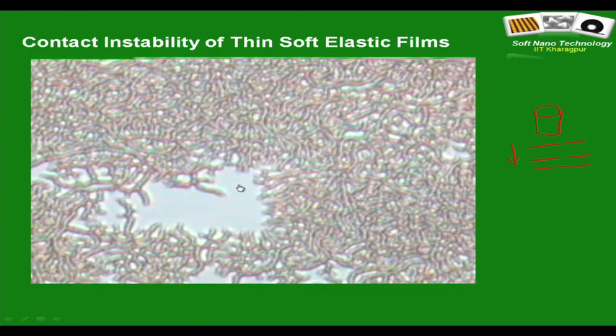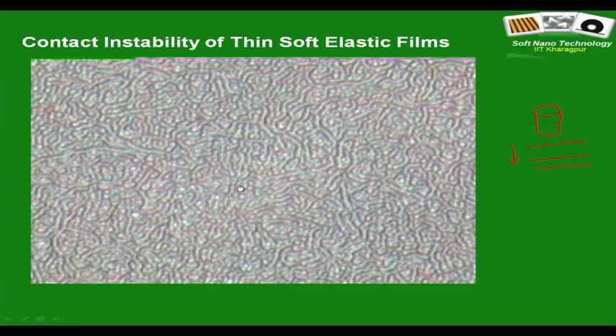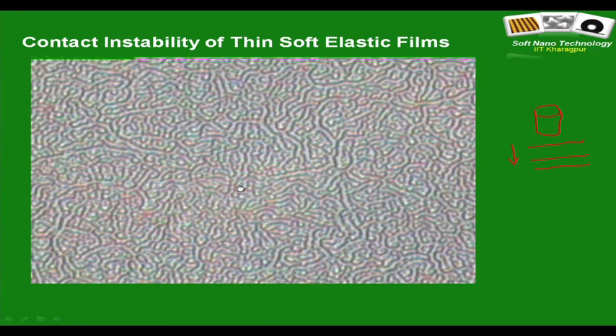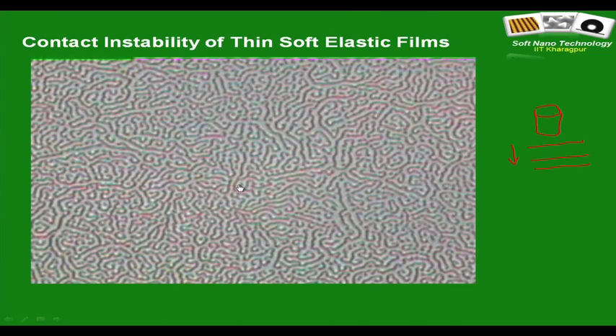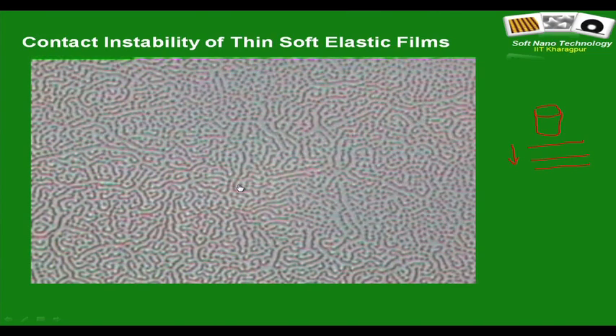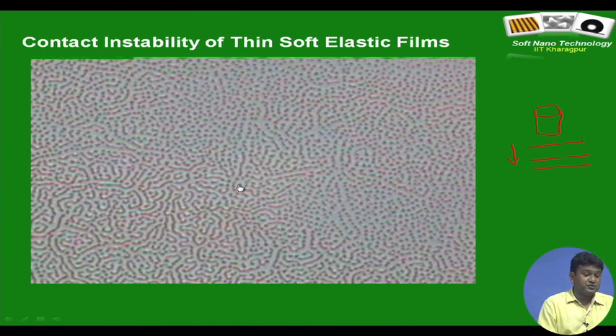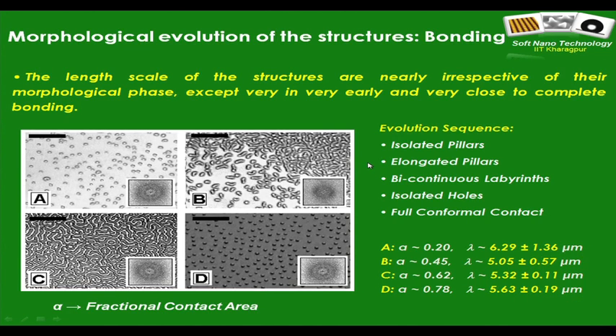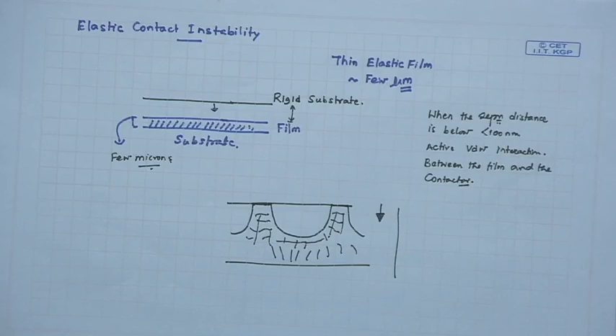Anyway, as the approach continues, you see a complete formation of these bicontinuous labyrinths, and even beyond this stage, further approach in fact leads to formation of isolated holes. So what are the things we observed? One important thing is related to the physical nature of the films. As I mentioned, as some parts of the film go and touch the contactor, the other parts sort of pull it back.